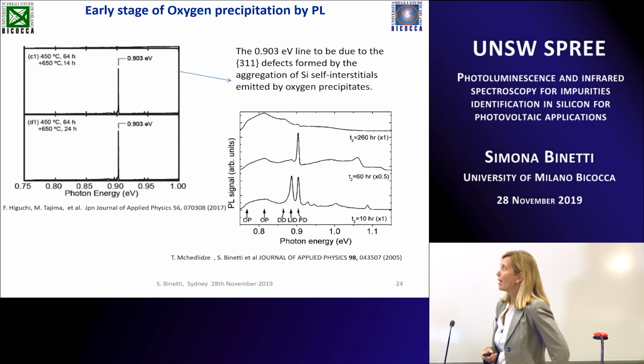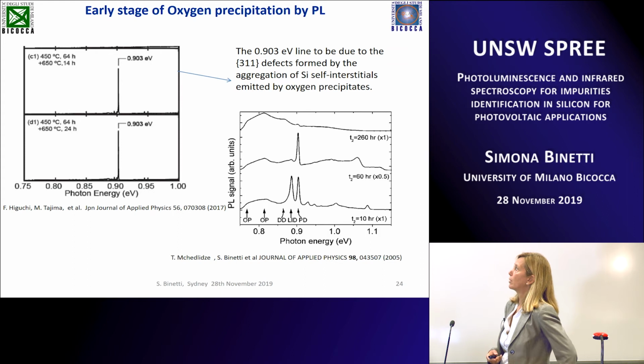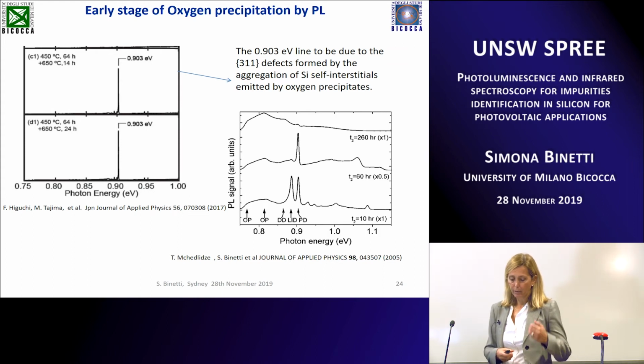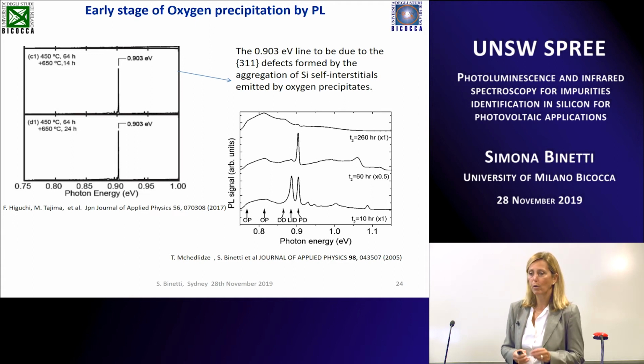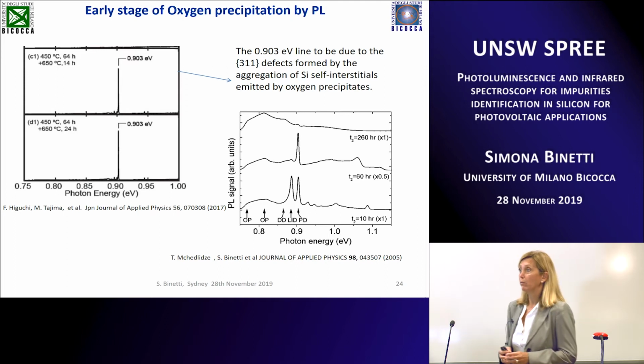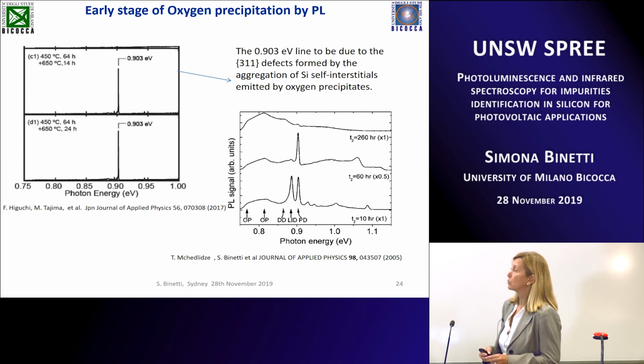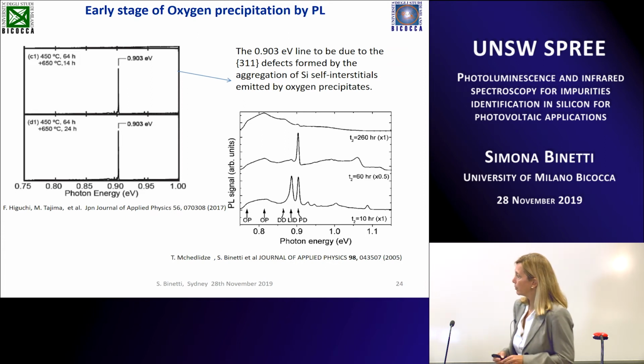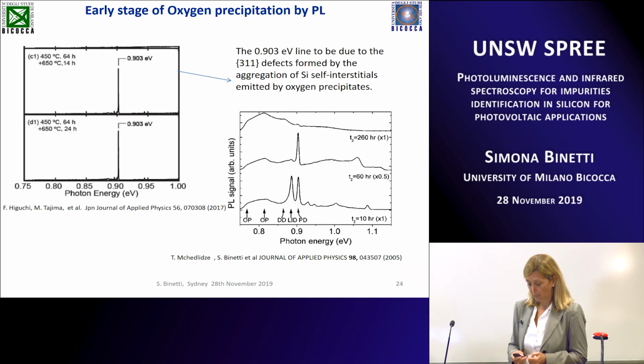It's also possible to infer something about the early stage of oxygen precipitation by photoluminescence, much before thermal donor formation. When you have just the initial process of precipitation, there is an emission of self-interstitials, because the molar volume of silicon dioxide is larger than the molar volume of silicon. So when you precipitate the silicon dioxide, you have an emission of self-interstitials, and these self-interstitials can aggregate to form the very well-known 311 defect, and this defect is responsible for a line at 0.903 eV that has also been associated to some defect in this work that we have done in collaboration with MIBSOLAR. We have made a correlation between this line and a defect that can be detected by electron paramagnetic resonance techniques.